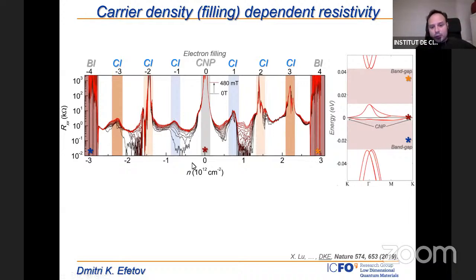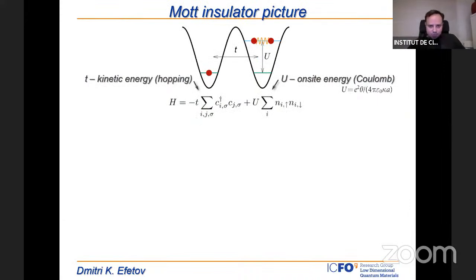When we look closer and convert the carrier density of these resistance peaks to electrons per unit cell, we find that these resistance peaks all appear at exactly 1, 2, 3, and so on electrons per unit cell. So these resistance peaks are not random, but well defined, coinciding with integer fillings of electrons or holes per moiré unit cell. These resistance peaks are absolutely not explained by the single particle band structure, but have a different origin. Currently we all believe that they have to do with correlations, with electron interactions in the system. The way we think about it is in the Mott insulator picture.